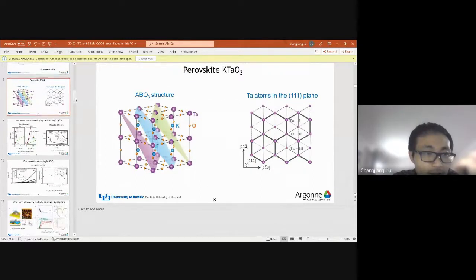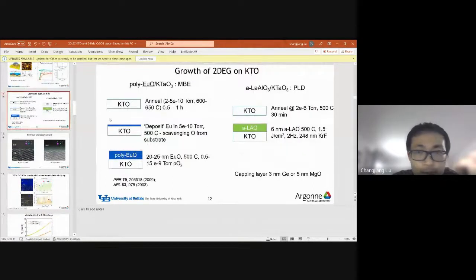Yes. So we use MBE to grow europium oxide, and also use PLD. Now, following our work, people can use sputtering to grow a thin layer of aluminum on KTO. They can also achieve a two-dimensional electron gas that is superconducting. So yeah, if you have a sputtering unit available, you can also grow a thin aluminum layer on top of KTO.